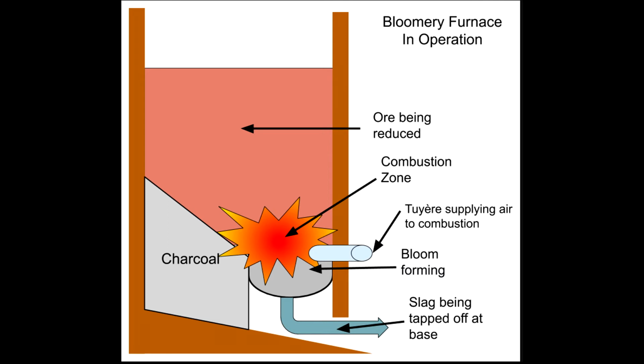To understand what that does for us, we need to get back into the chemistry. The charcoal, a nearly pure mass of carbon, takes some heat and some oxygen from the air and produces carbon dioxide, and a bunch more heat, which both heats up the iron ore we've stacked on top of it and the rest of the charcoal, which will react with the first oxygen it meets to repeat the process. But this process is rapidly going to be oxygen-starved. This is important. And so, some of these reactions are going to produce carbon monoxide, which then, because it is very hot, goes racing up through our iron ore.